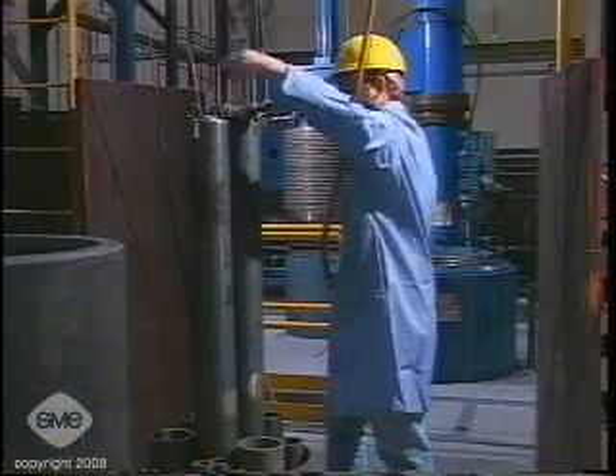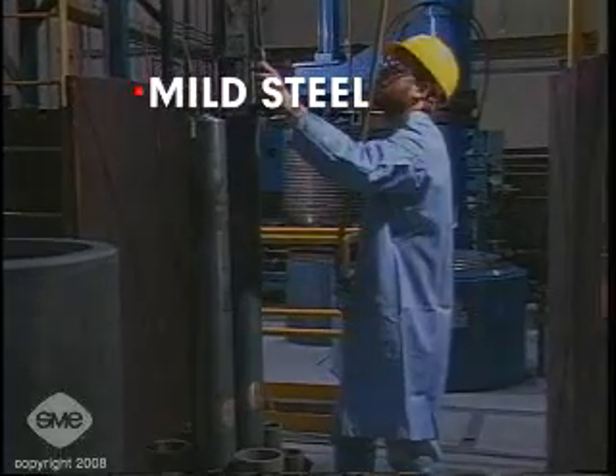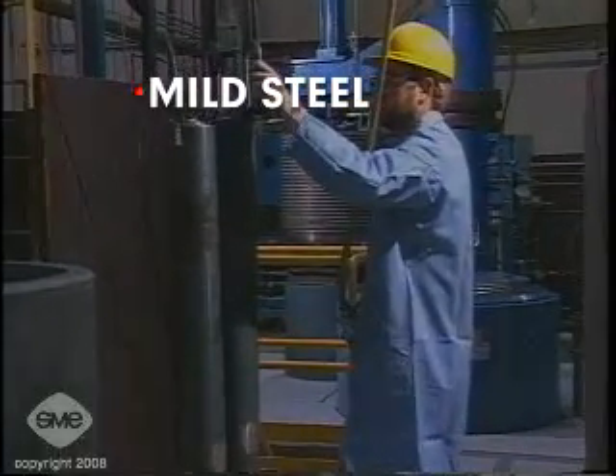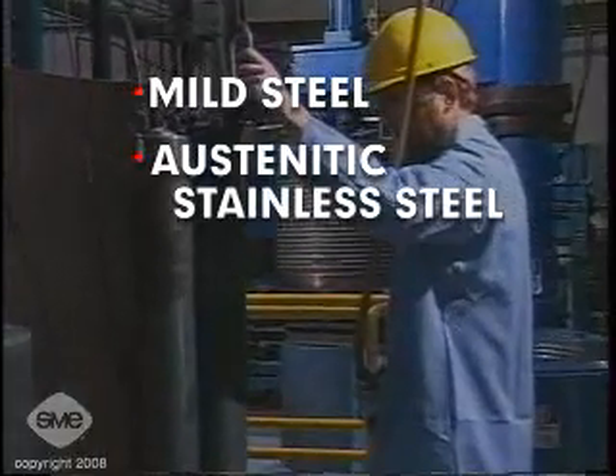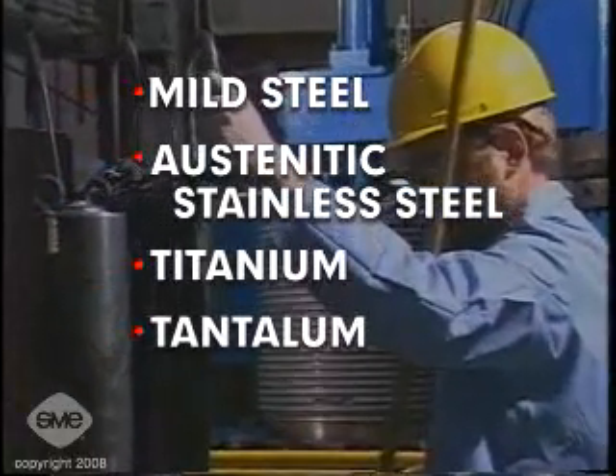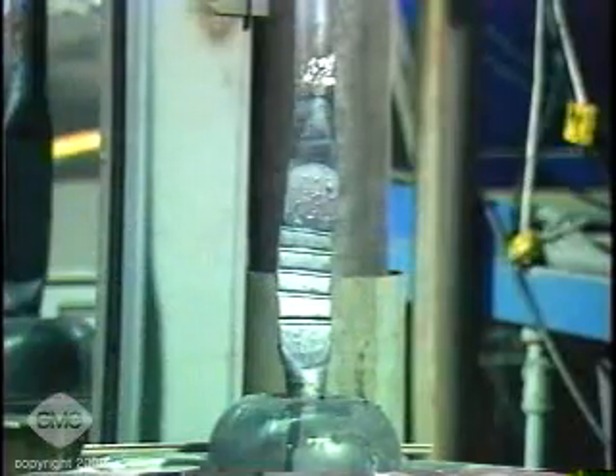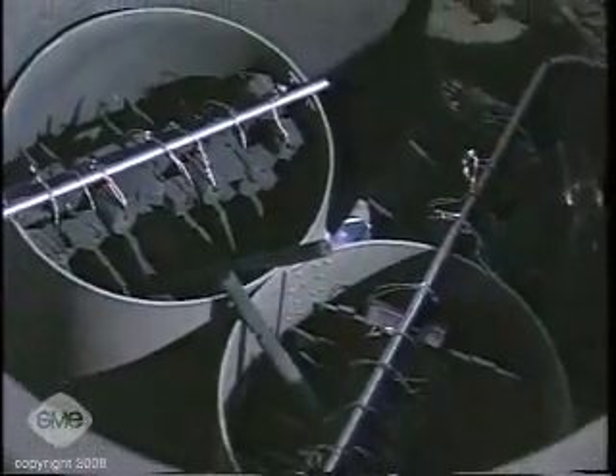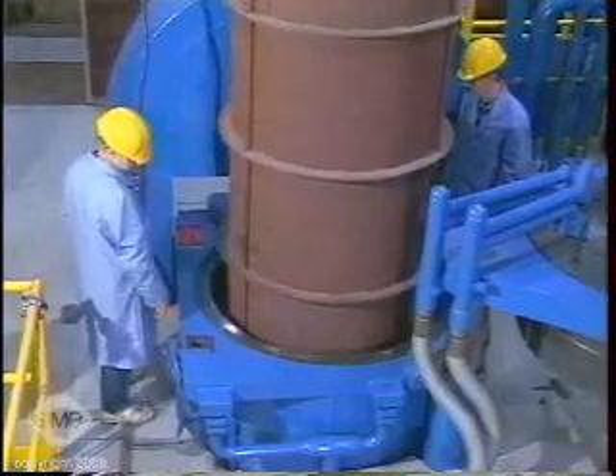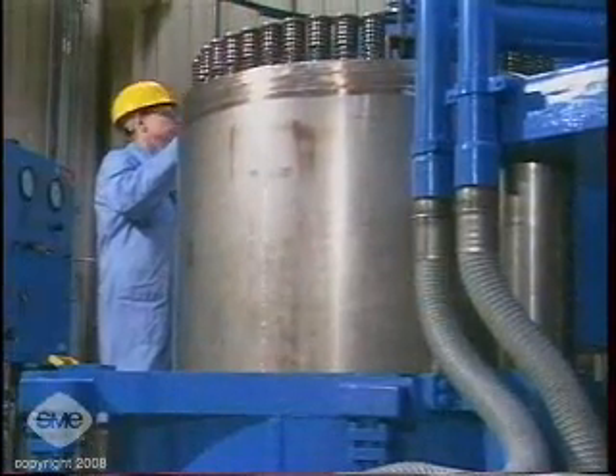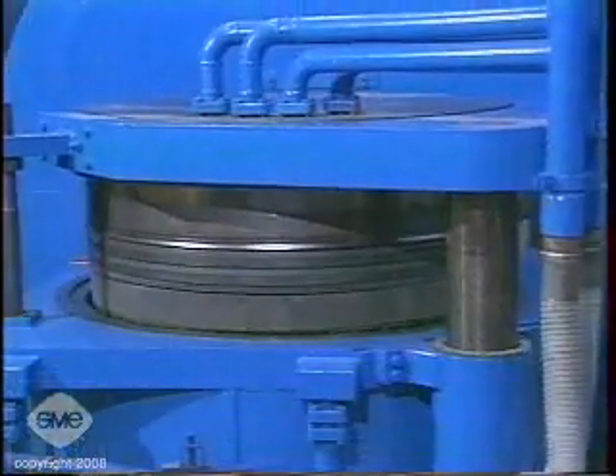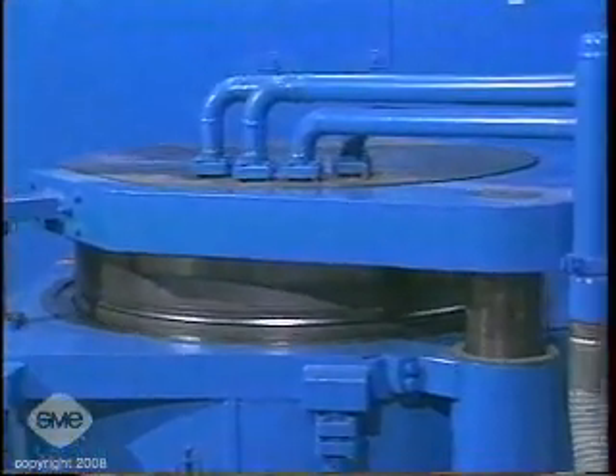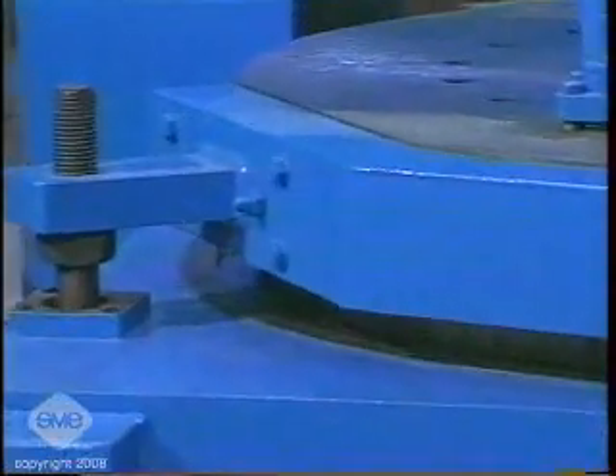Powder is placed in pre-shaped sheet metal molds. Mild steel is the most common mold material. Others include austenitic stainless steel, titanium, tantalum, and copper. For complex shapes, the molds are usually welded fabrications of formed parts. Once filled, the molds are evacuated, sealed, and then assembled into fixture cans, which are lowered into the pressure vessel. The furnace is placed over the vessel, completely surrounding the molds, and sealed. Heat and gaseous pressure are then applied, consolidating and sintering the powder in a controlled atmosphere.